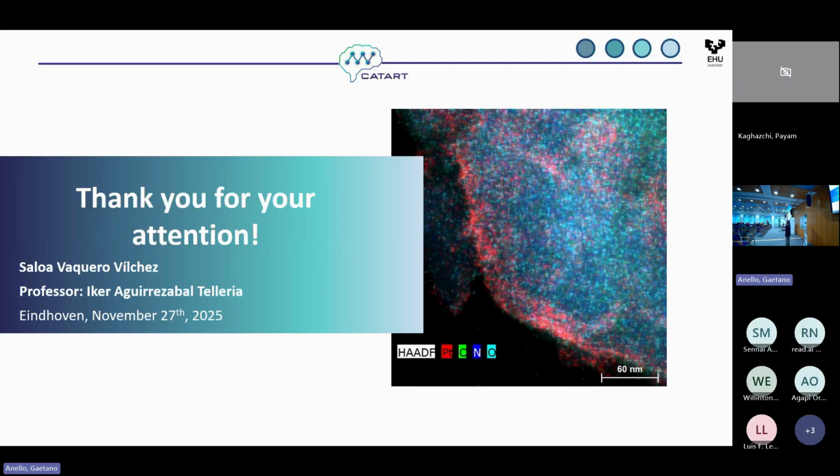And we've made some really nice C3N4 with ideal ratios, and it's not as good as something that's not stoichiometric. So it's worth just doing the CHN analysis. And if it's not quite C3N4, it often works much better. So we spent a lot of time making it really nice, and it wasn't as good a photocatalyst. So it's amorphous. It's not perfectly C3N4, and everybody assumes it is, but it's not quite. That happens in many systems. One thing is what you see in the slide, one thing is reality.